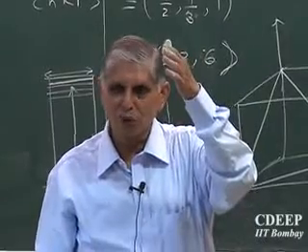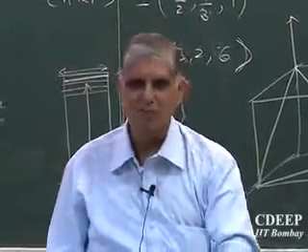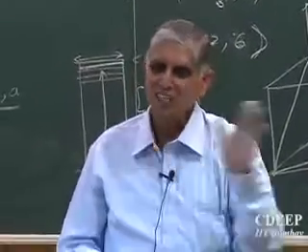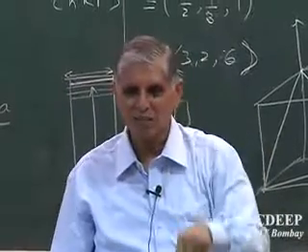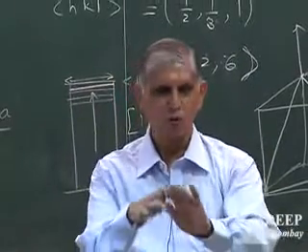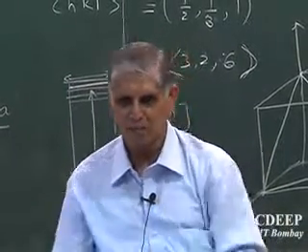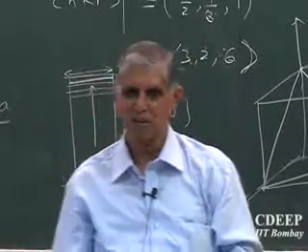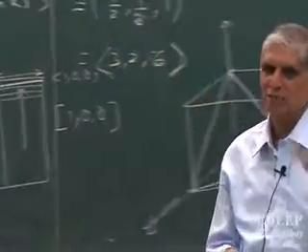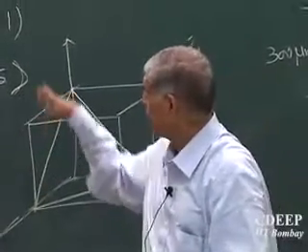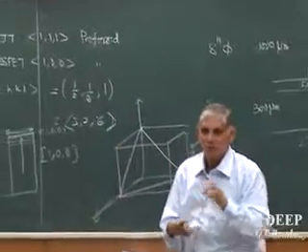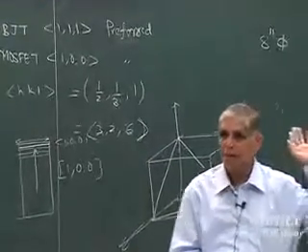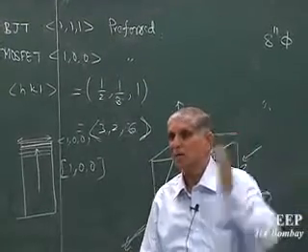So stress travels from top to bottom. In the same way, silicon is also broken. If I scribe silicon and from the back side I roll with a rubber, it will break into pieces exactly along the line I put on the top. That is also done with diamond scribers. So this fact that we need to scribe is also helped by the availability of planes, otherwise I cannot cut.